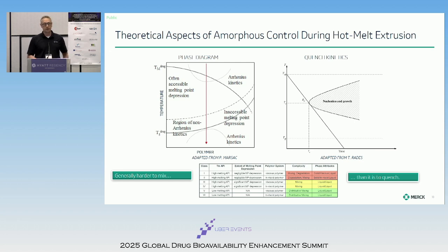We can break it down into phase diagrams that essentially describe what's going on in the extruder, where really what you're looking for is melting point depression, and you're coupling that with the rheological characteristics of your formulation. So another colleague at Merck, Greg Troop, had developed what we term the Troop classification system, where we categorize the melt extruded systems in terms of the extent of melting point depression, and then also the rheological characteristics of the